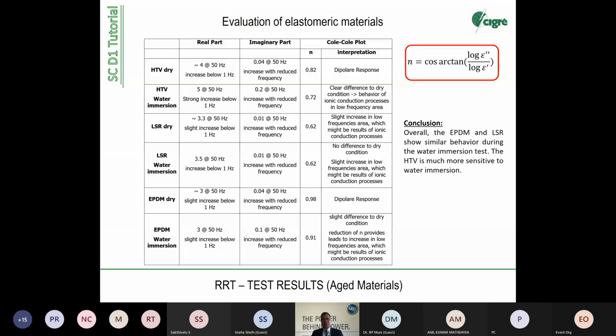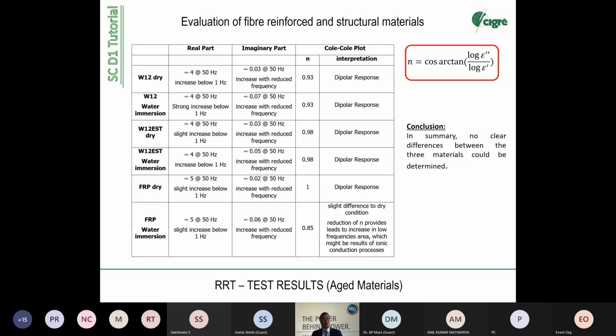Here we studied fiber reinforced and structural materials just by interest. It was not in the scope because the material itself was not defined here, but we have taken typical materials that are used in high voltage power apparatus, because we do not want to study a material that has no value for the industry. So most of these materials show a clear Debye response, a dipolar response with N close to 1.